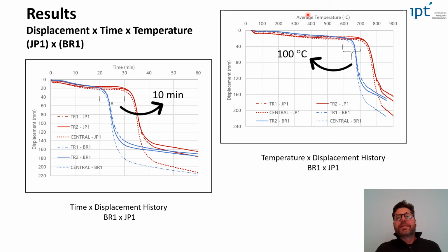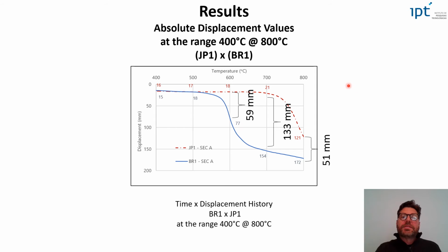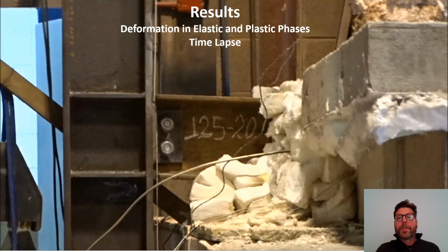And what we saw is that the same curve shape was seen for the other pairs of samples. Here we can see the absolute displacement values for both steels at the temperature range of 400 degrees to 800 degrees, with the biggest difference occurring around 700 degrees. Again, the red curve stands for the JP1 sample, and the blue curve stands for the BR1 sample, being the JP1 the Japanese fire-resistant steel sample, and the BR1 the Brazilian conventional steel sample.